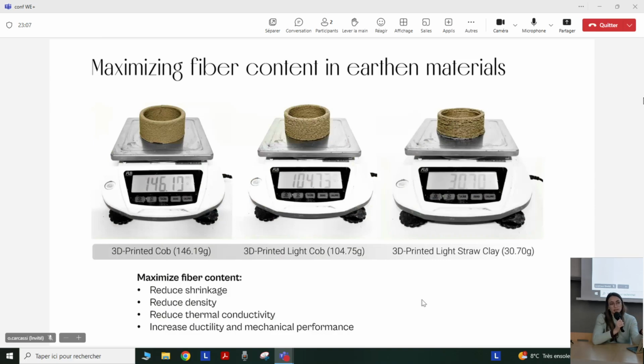So you have to think that the limitation of adding fibers in 3D printing is really related to the viscosity of the materials. You have to have a paste that is extrudable, but you also need to work with the pumping system. So it's not just about adding fibers. You really try to understand all the constraints inside this technology. And the reason why we wanted to maximize the fiber content, of course,